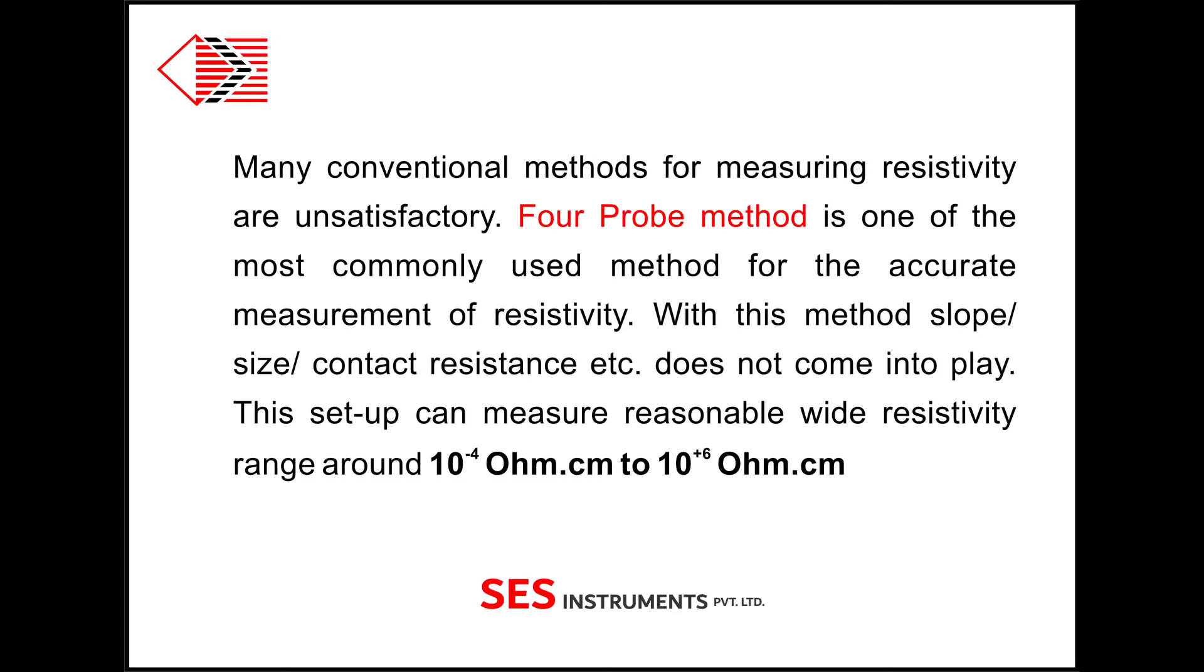Many conventional methods for measuring resistivity are unsatisfactory. Four probe method is one of the most commonly used methods for accurate measurement of resistivity. With this method, slope, size, contact resistance, etc. does not come into play. This setup can measure reasonably wide resistivity range around 10 to the power minus 4 ohm centimeter to 10 to the power plus 6 ohm centimeter.